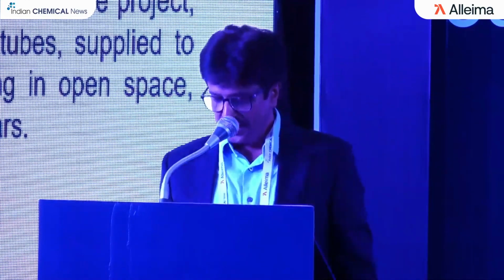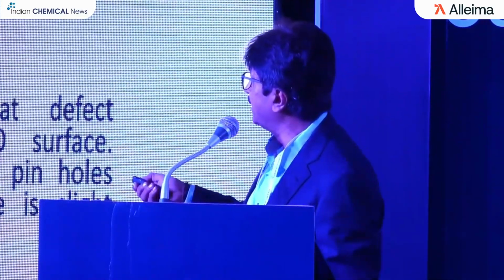And people then blame the tube manufacturers. So, same case, such severe pitting of a good material happened. I would say this is a murder of the material. This has not even gone to the plant. It's not put into service. So the case came to me, we did identify and we found out that there is a typical tunnel corrosion. Can you see it in the scanning electron microscope image? There is a tunnel which is formed. This is a typical indication of microbiologically induced corrosion, MIC. So this was MIC.